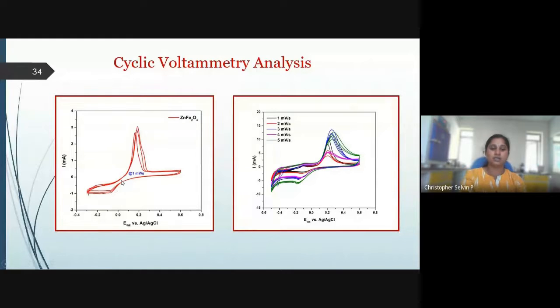These are the CV patterns obtained for this particular sample, and we can say well separated and sharp reduction and oxidation peaks for zinc ferrite nanoparticles, and this one is the sample CV recorded at 1 millivolt per second scan rate. We could vary the cyclic voltammetry for different scan rates, and the system was completely reversible. However, compared to this one, we could see a shoulder-like peak at 1 millivolt per second scan rate. As mentioned in the FTIR analysis, this may have arisen out of the metal hydroxide interaction, but this vanished on repeating the cyclic voltammetry analysis for different scan rates. So we need not bother about this shoulder peak.